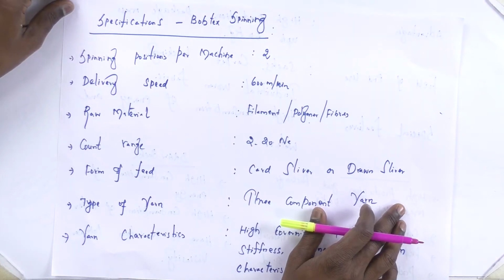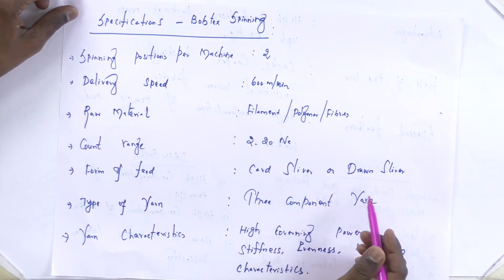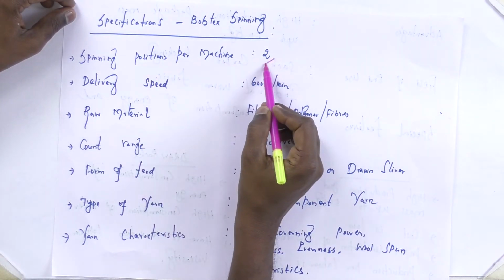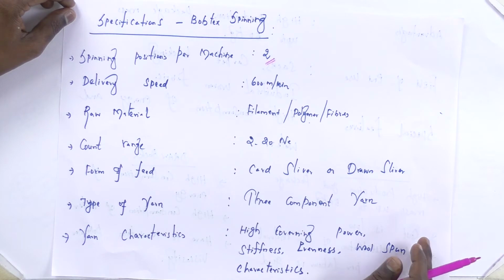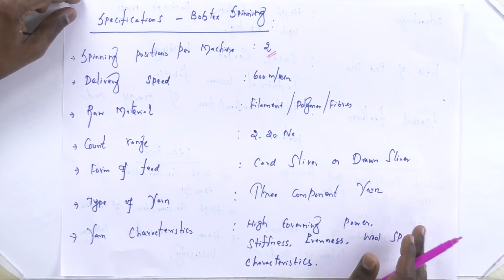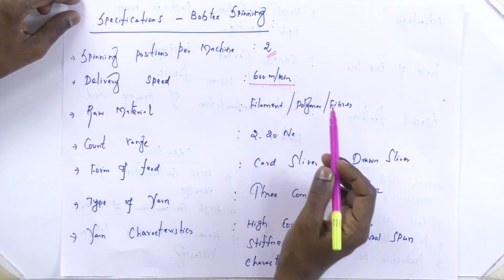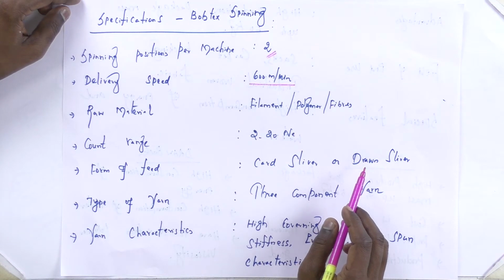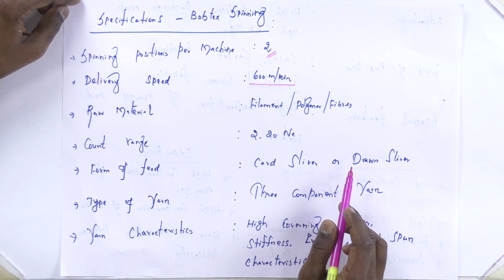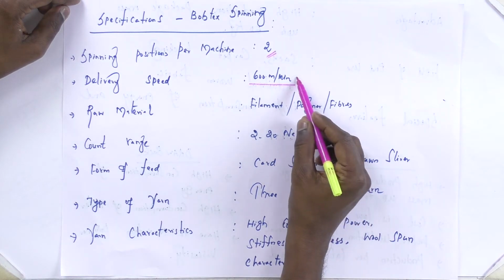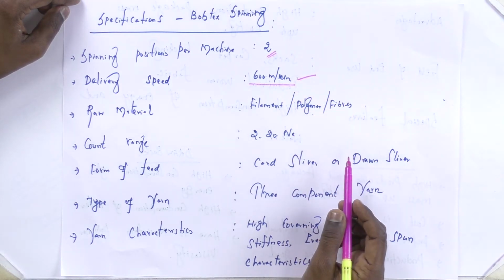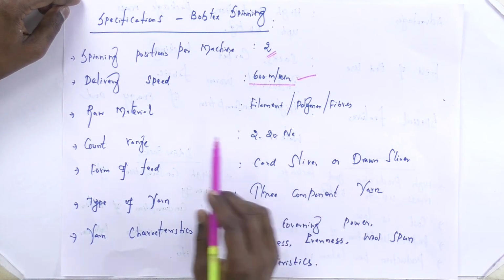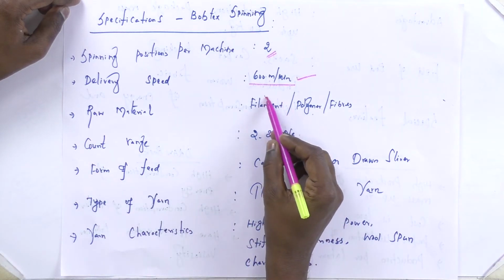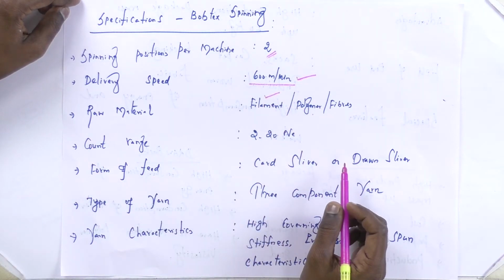So specifications of Bobtex spinning yarn. The spinning position per machine is 2 spinning positions. The delivery speed is 600 meters per minute. It consists of less rotating parts, so we can go up to high speed. The 600 meters per minute is the delivery speed of a Bobtex spinning system. The raw material used is a filament. We can use polyester filament or nylon filament, any type of filament yarn.